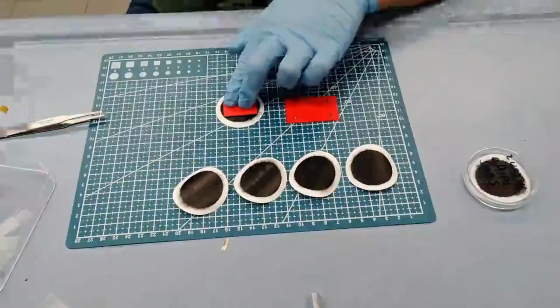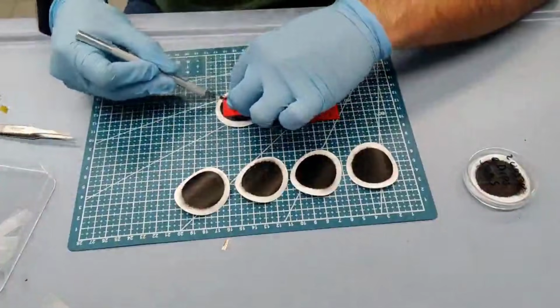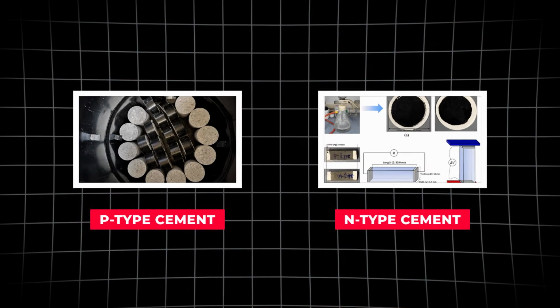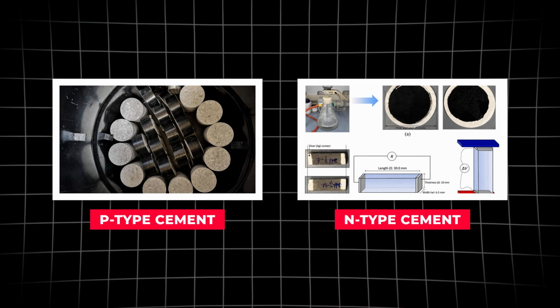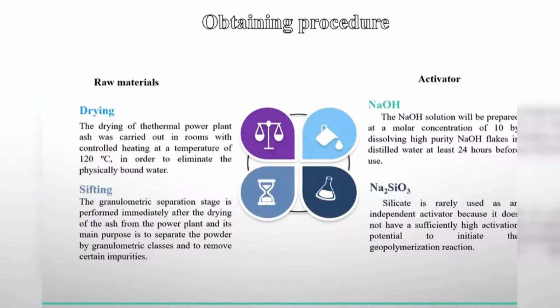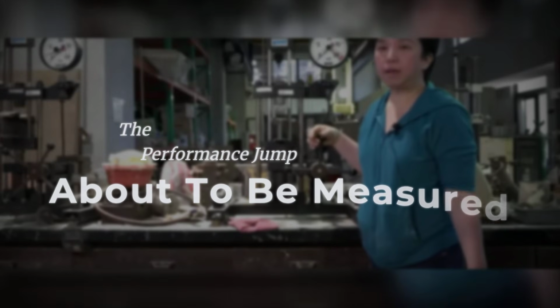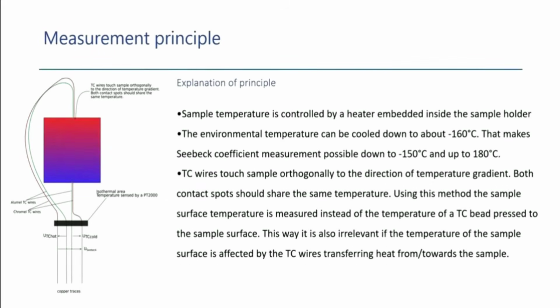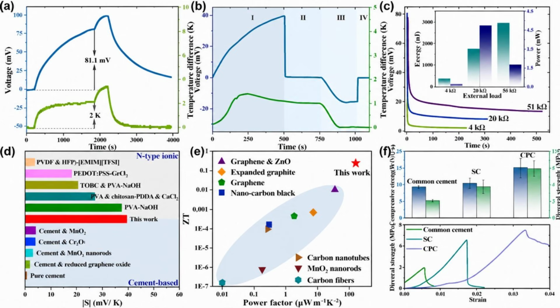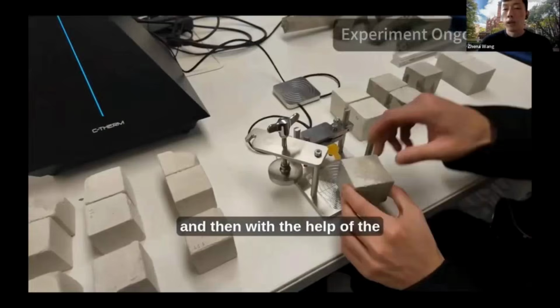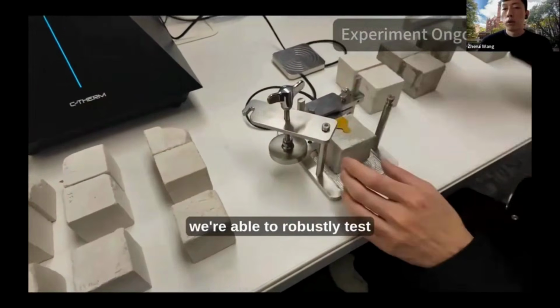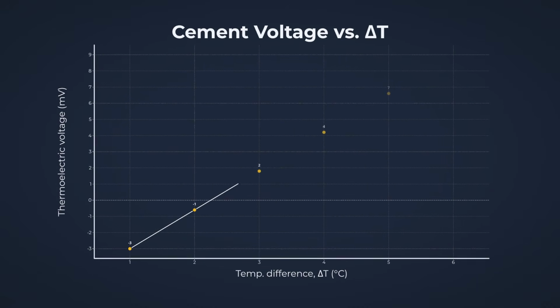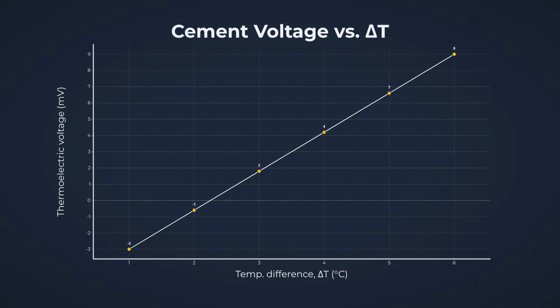So the Southeast University team, led by Miao Changwen, an academician of the Chinese Academy of Engineering, spent their effort engineering the cement itself to be good at it. They built 2 versions, a P-type and an N-type, the 2 halves you need to make a working thermoelectric circuit, by mixing special additives into the cement matrix. And the performance jump is the headline. Their thermoelectric cement hit a Seebeck value around 10 times higher than earlier cement-based materials. In plain terms, for the same difference in temperature, it produces roughly 10 times more voltage than anyone had gotten out of a cement before.